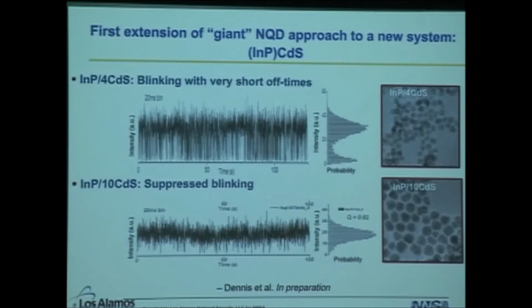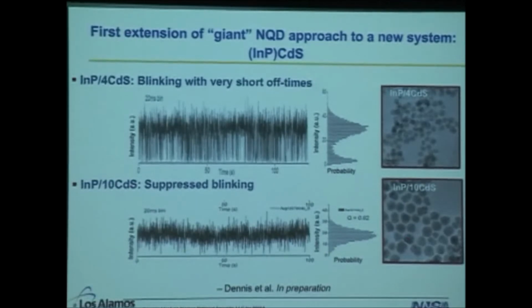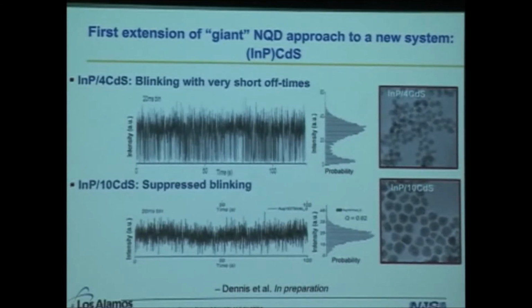And so we've been focusing quite a bit on the indium phosphide-based systems, initially with the idea that indium phosphide is more benign compared to a cadmium selenide core material, and so biologists will like it better and so on. But of course, the system that's working best right now happens to have a cadmium sulfide shell. So whatever, the physics is still interesting. This is the first extension of the, quote, giant concept to a new system. And you can see we are, like the other system, growing thick shells in a nice fashion. They're not quite as pretty yet, but pretty good. And we have very tantalizing new evidence that these systems are also exhibiting unusual behavior.